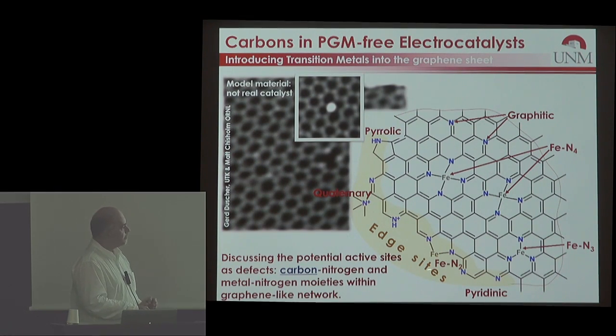In all cases, however, the iron that we think of is coordinated with nitrogen, and we'll show you that there is a correlation between these two moieties in the graphenic material. I will only use the word moiety because none of these are actually chemical species. These are defects, and they exist only in the context of the graphene sheet. They are not really present as freestanding molecules, and they can be equilibrated mathematically only if you assume periodic calculations. Now, you can see that these moieties, or these essentially vacancies, when you have a single vacancy with the three nitrogen substitutions, are rather symmetric, that means relaxed. So they don't disturb the system.